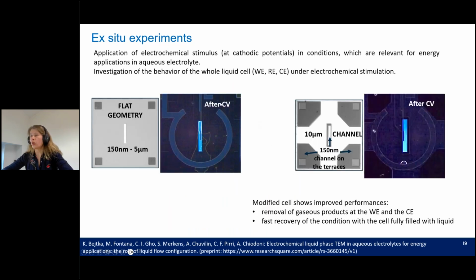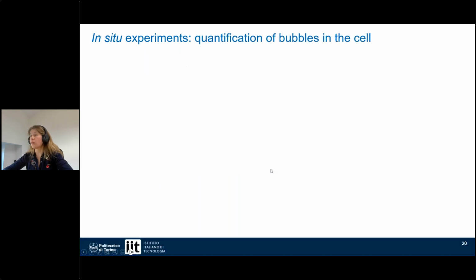And here I show you the situation after the experiments are run. We remain in the standard configuration for quite a lot of time with the bubbles sitting there, while the gaseous products are efficiently removed from the working electrode area and the counter electrode area in the modified cell. So we have a fast recovery of the condition with the cell fully filled with liquid in a very short time.